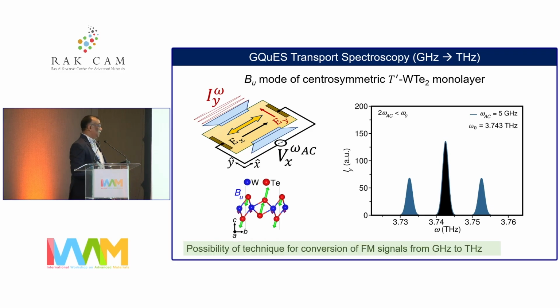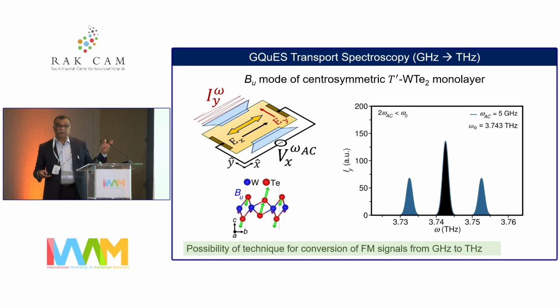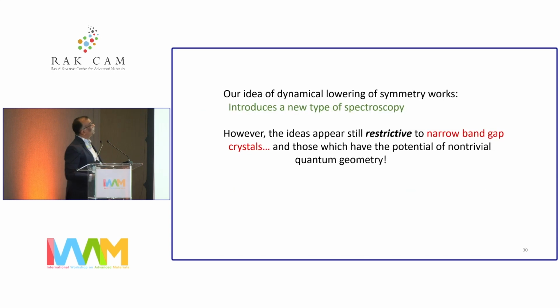Okay, so this possibility opens up a technology that if you have frequency modulation in gigahertz, you can transduce it to the terahertz frequency range. And that's also a very important tool because there are very few sources and detectors in terahertz frequency range, and this technique allows you to go from gigahertz to terahertz frequency range. Okay, so our idea about dynamical lowering of symmetry works, but unfortunately, these ideas appear to be still very restrictive.